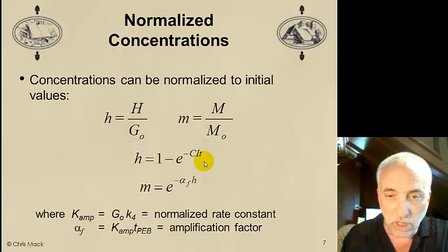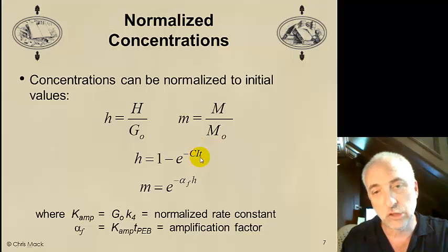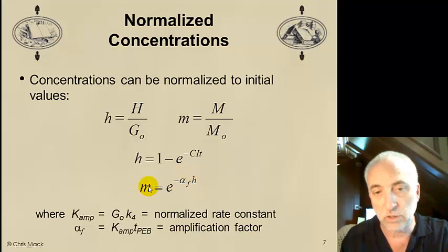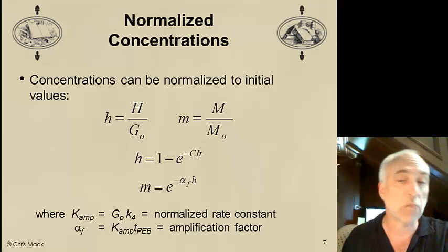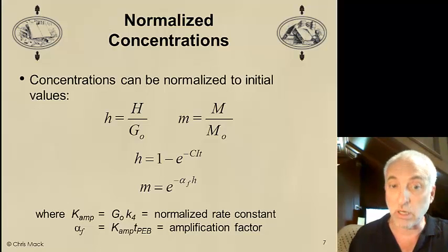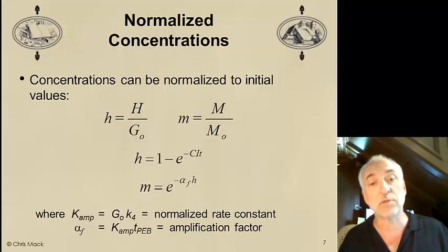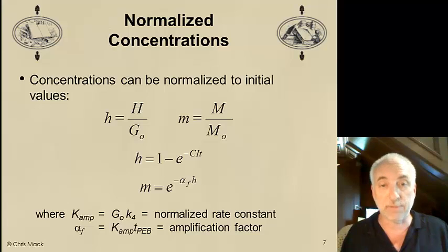Now, what do these two coupled equations tell us? First, I have dose that generates acid. And then I have amplification that turns the acid into amounts of deblocking. The amplification factor can be higher or lower depending on the time and temperature of the bake. If I increase the time or the temperature of the bake, I get more amplification.